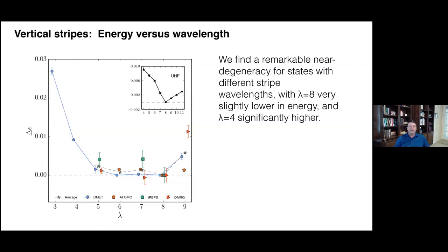So a key result here is, first of all, this general agreement was finding that all of the states were striped. And then this key issue of the amount of holes, the filling per stripe, was nearly degenerate. So this lambda here is the spacing between the stripes. In this particular filling, the stripes at a spacing of 8 are filled with holes, so one hole per unit length of stripe. Over at 4, this is one hole per 2 unit length of stripe. And you can see that over at 4, the energy is noticeably higher. But once you're a little bit higher in energy, you have this very close near degeneracy.